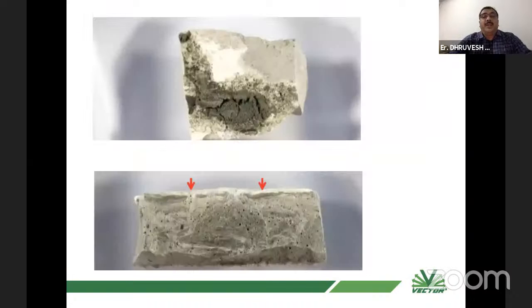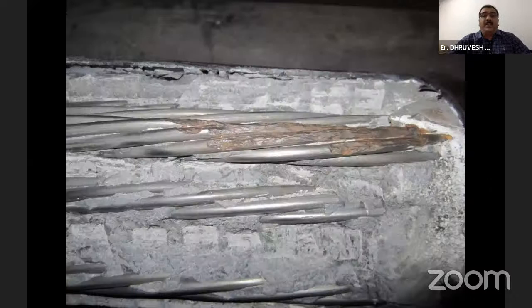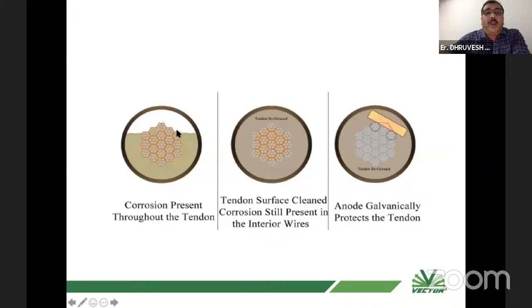It has been found that wherever at the periphery, like at the junction between the old and the new grout, you will find that the top of the strand wires start corroding. So in such a case, when you have voids and you can see that there were two different grouts and the surface started corroding. This picture shows it well, there was a void which was grouted, and then what you can do is simply put a flat anode here. This is how it has been connected. So there will not be any incipient anode formation, and you can protect the entire tendons from corrosion.